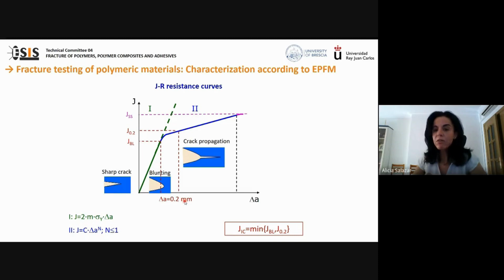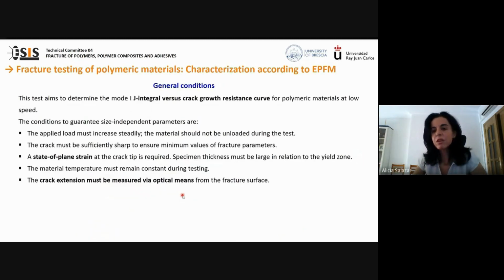The initiation value of the J integral of fracture toughness is obtained as the minimum of the following values. J blunting, JBL, is obtained as the intersection of the blunting line with the JR curve, and J 0.2 is the J value at a crack growth extension of 0.2 millimeters. This value is completely arbitrary, but it combines two facts. One, it is small enough to be close to the crack growth initiation, and secondly, it is large enough to be measured by optical means. The aim of this test method is to determine the mode 1 J integral versus crack growth resistance curve for polymeric materials at a low speed.